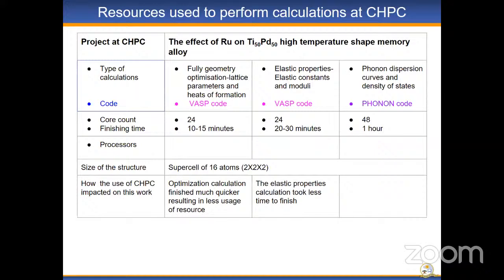There are some various slides here, which I'm not going to go into detail about, just to show that we're using various codes to do our calculations. What is important to note is that for the 24 core, an optimization calculation can take about 10 to 15 minutes, which is actually good, depending on how big your system is. For this one, it was the ternary system, which of course one will expect to run a bit longer. 10 to 15 minutes is very reasonable. When we are doing other properties like elastic constants and all that, it can take up to 30 minutes.